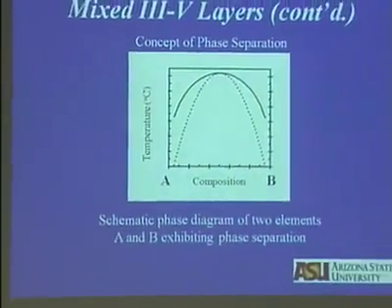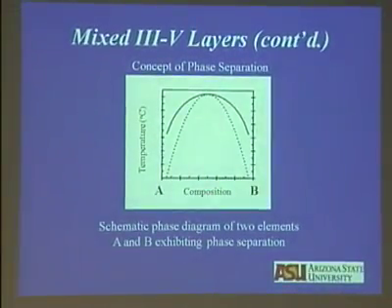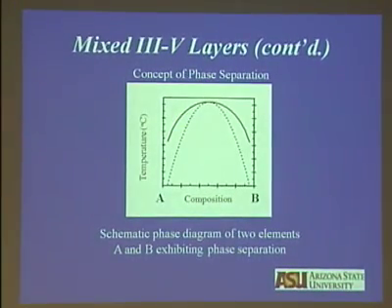Now, just to give you the background, what is phase separation? Phase separation is when you have a solid solution, and that composition free energy diagram has inflection points, and you cool that material. It doesn't get to these end members, but the solution decomposes into A-rich regions and B-rich regions. That's what we refer to as phase separation in material science. It's in physics or material science. That's just an introduction to the issue of phase separation.